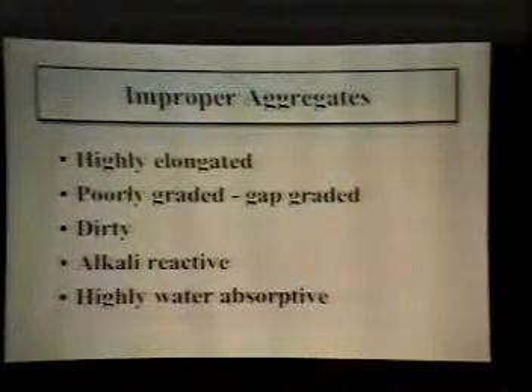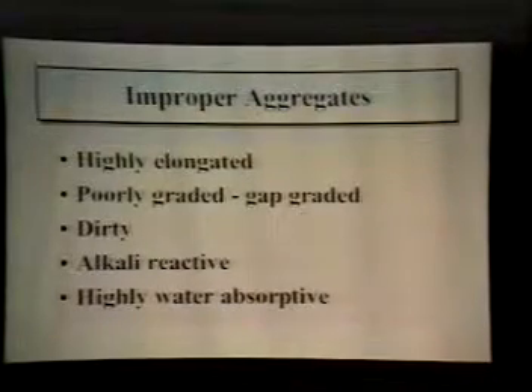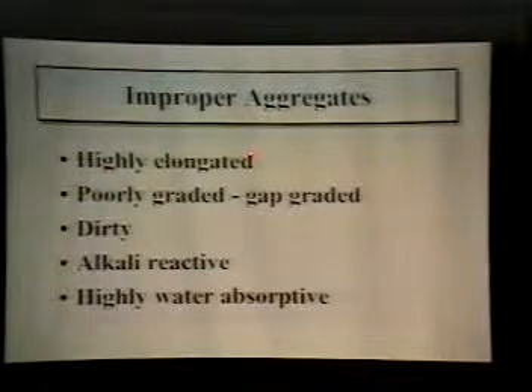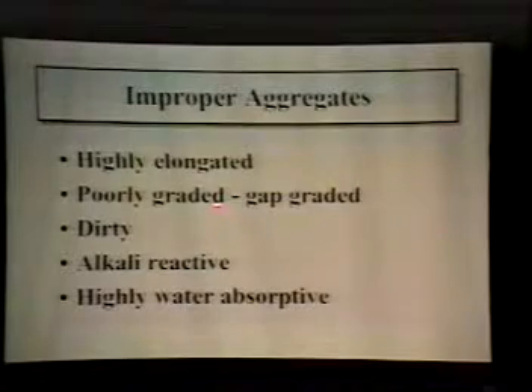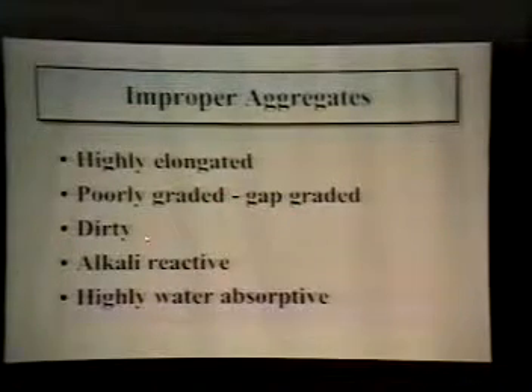Let's start with some improper aggregates. What would they look like? Well, they could be highly elongated, poorly gap graded, they could be dirty, they could be alkali reactive, or very porous aggregates. Elongated aggregates. As you can see, these are all elongated. The aspect ratio of these aggregates is about 4:1 or more, and it has about 40% in the mixture.